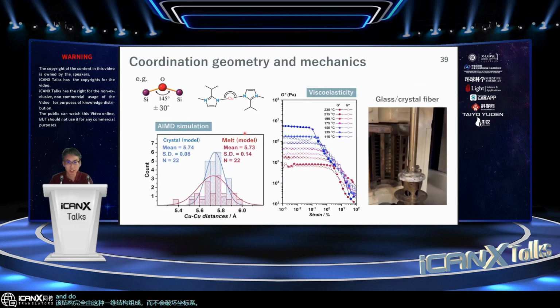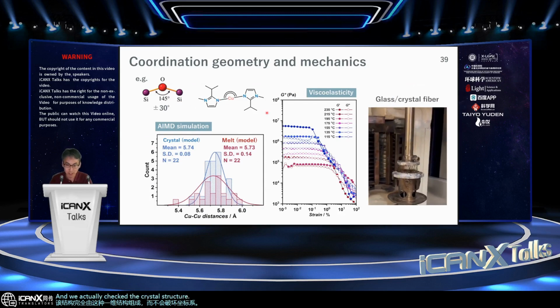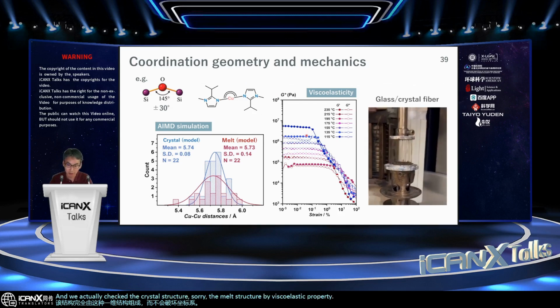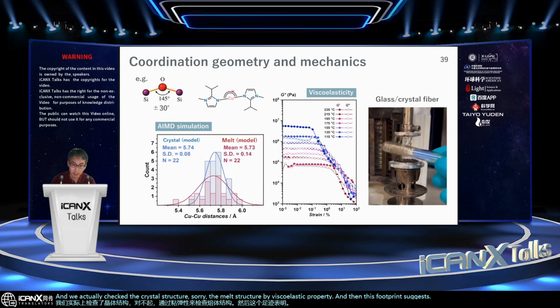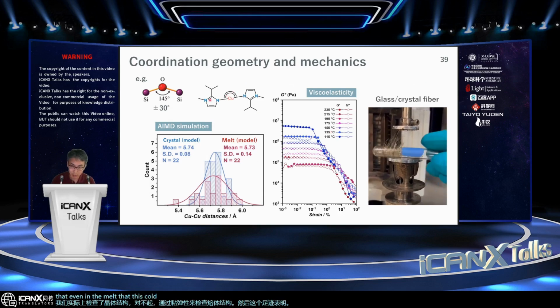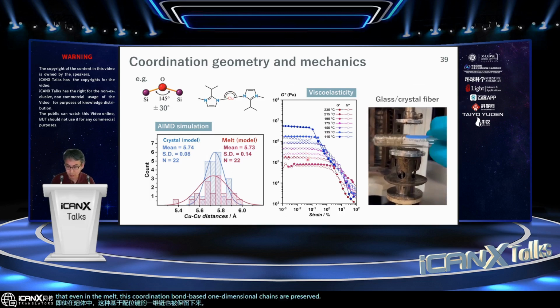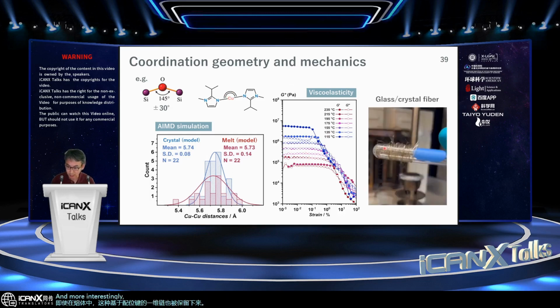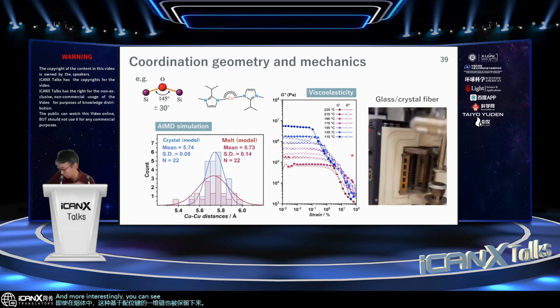And we actually checked the crystal structure, the melt structure, by viscoelastic property. And this footprint suggests that even in the melt, the coordination bond-based one-dimensional chains are preserved. And more interestingly, you can see the movie, I hope.